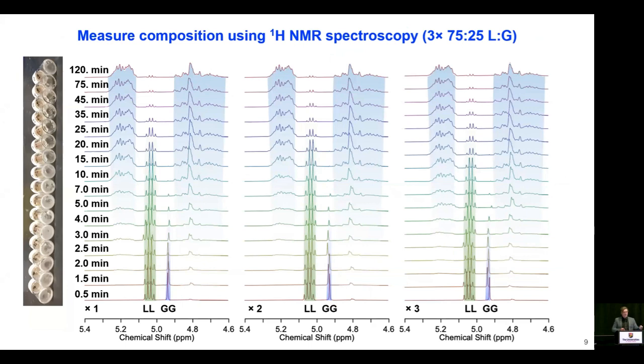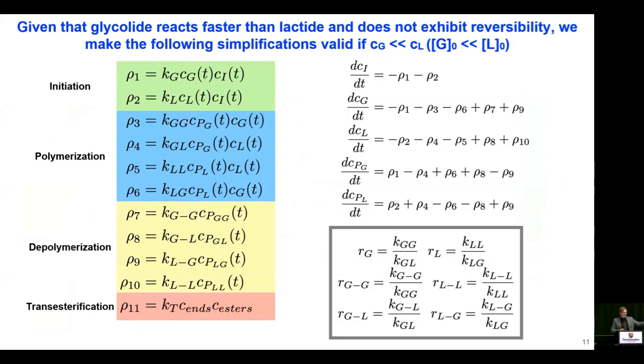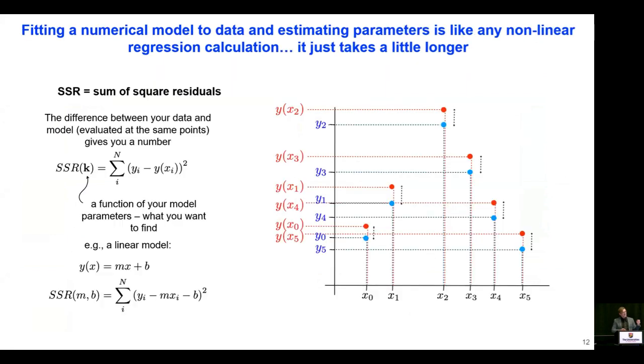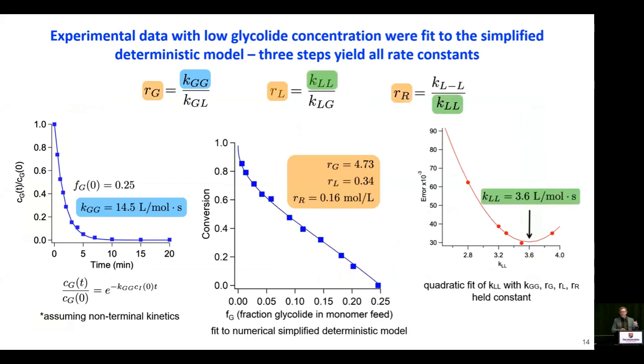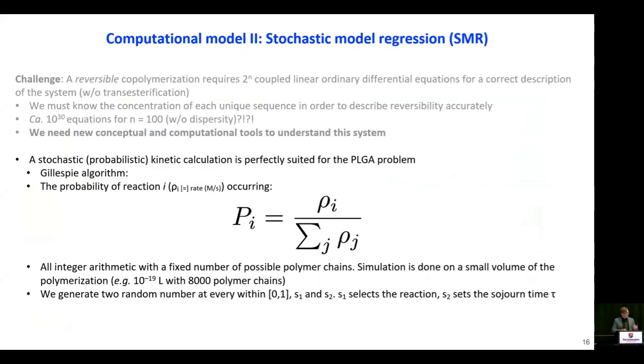So now we move to a computational method that actually matches the complexity of the system, and that is the stochastic model regression. Rather than calculating anything deterministically, we do this in a probabilistic formulation where each reaction at a unit time has a certain probability of occurring. We calculate based on that page of equations that I showed you earlier. In this case, we're essentially doing a simulation of the polymerization.